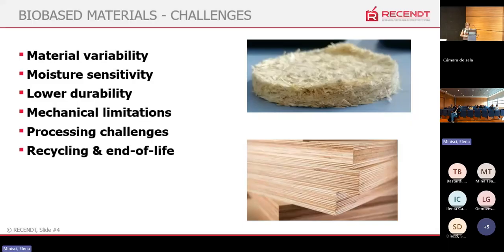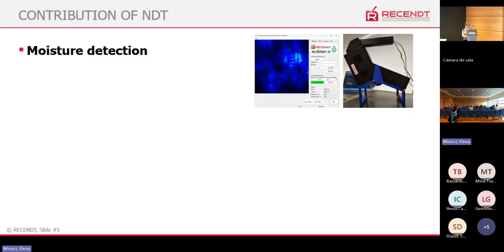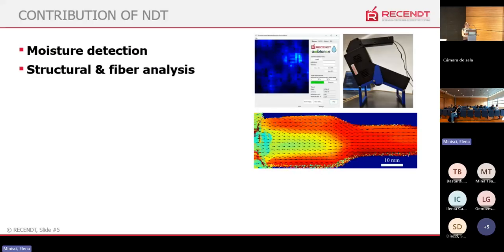Also, some materials are easy to recycle, but some of the bio-based materials are not easy to recycle because of the combination of fiber, fossil-based and bio-based components, and also because of the end of lifetime. This is where NDT can help to contribute. We can easily detect moisture with many kinds of detectors, not only on the surface, but directly through the whole sample. We can analyze with non-destructive testing methods the structural combinations and the fiber orientation, and give information about the mechanical properties, their strength, and so on.